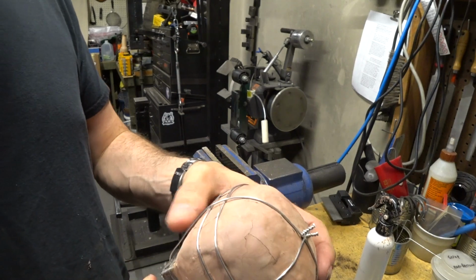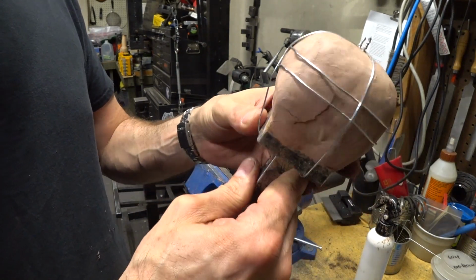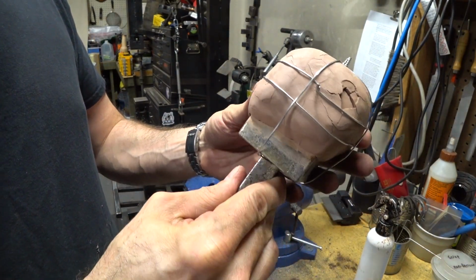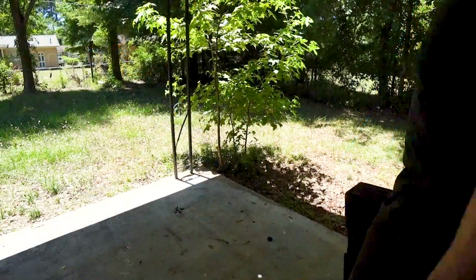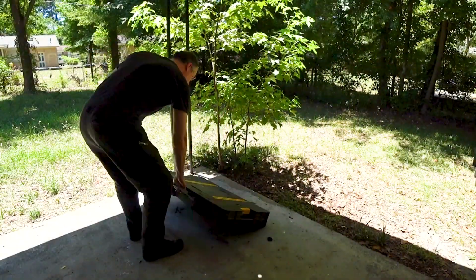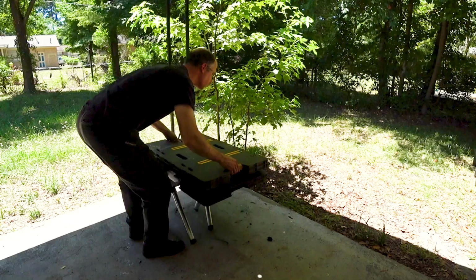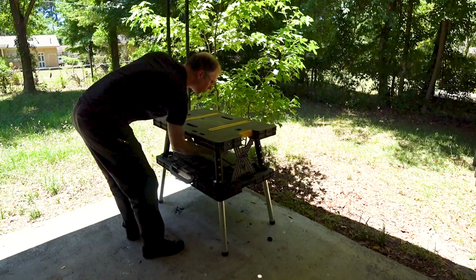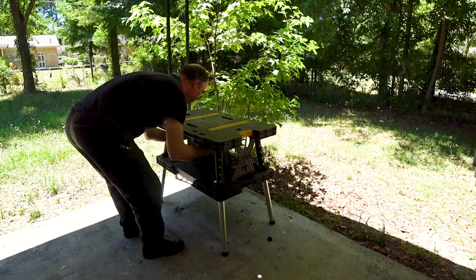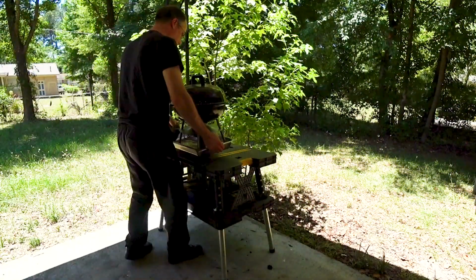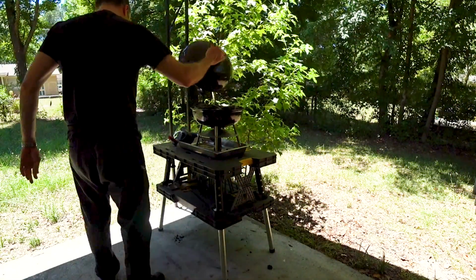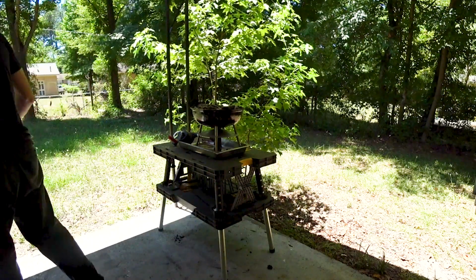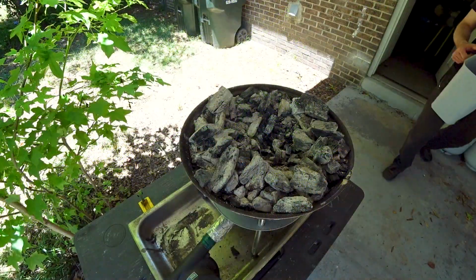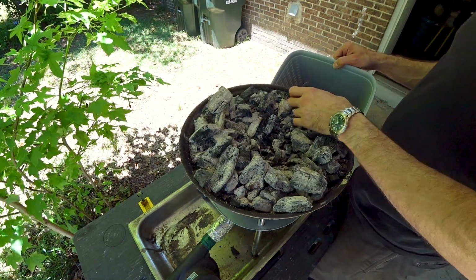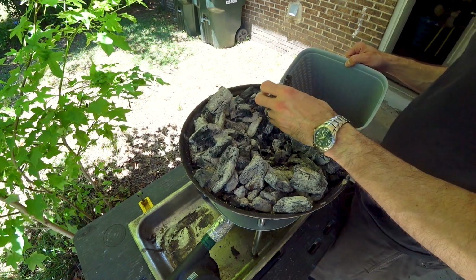So now we've got that clay layer bound on there with the stainless steel wire nice and tight. Hopefully it won't be able to crack and break away in the fire. In order to form a hard case on the outside of a piece of steel using this method, you need to be able to get the carbon to penetrate into the steel. This is only going to happen at austenitizing temperatures, which is about 1450 degrees Fahrenheit roughly. Before we can start a fire in order to heat that steel up to the proper temperature, we've got to clean out the old charcoal and ash from the last fire.